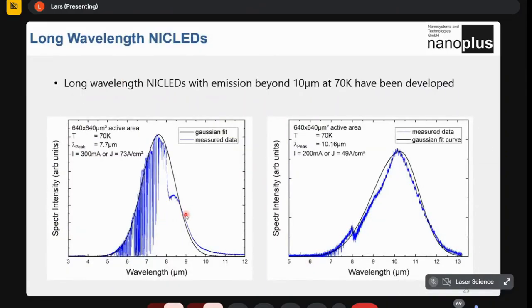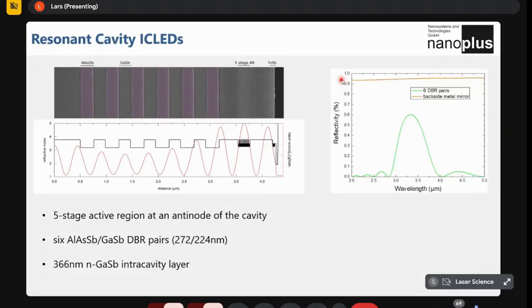Also here, the wavelength can be shifted. The 10 micrometer LEDs are at 70 Kelvin, right? So they are at liquid nitrogen temperatures. Nevertheless, you get light at 10 micrometers. This is needed for some applications, but the excessive cooling, of course, is quite expensive. So you cannot use this, of course, in a very low-cost system.